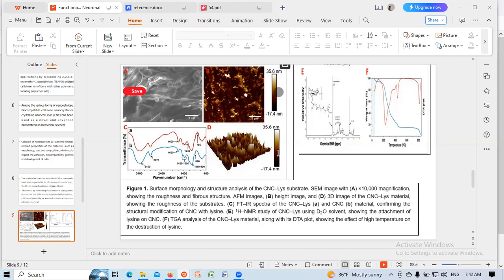In the 1H NMR analysis, the proton peak is at 1 to 5 ppm, with an anomeric peak at 4.6 ppm, which is an overlap due to the solvent. In the TGA analysis, at 50 degrees Celsius the initial loss of weight is 3%, and the major weight loss occurs at 250 degrees Celsius, with final weight loss at elevated temperature.